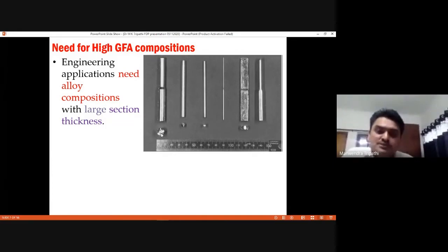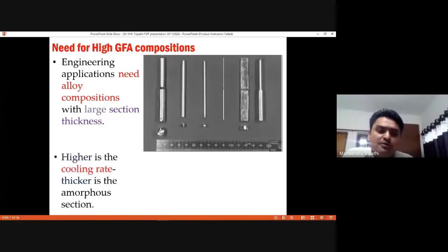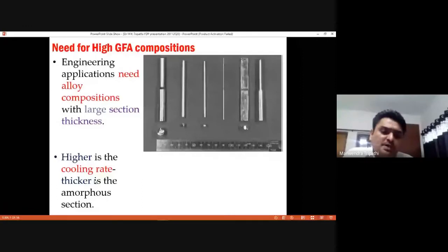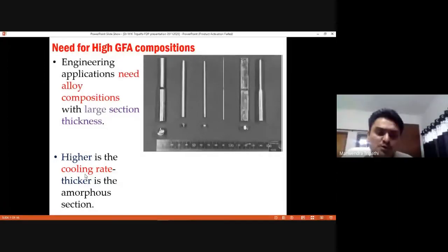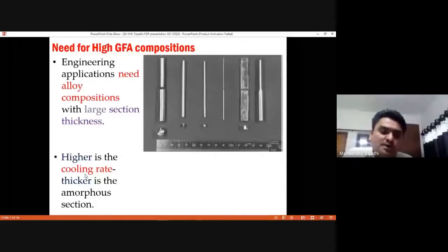So different compositions can have different glass forming ability, right? And it is measured sometimes in terms of the critical diameter. The higher the diameter for a given composition, the better the glass forming ability. And higher the cooling rate, the critical section thickness, the amorphous thickness, will increase, that we understand. But there is an engineering limit to increasing the cooling rate, that we understand. So we should compare various alloys keeping the cooling rate fixed, okay?